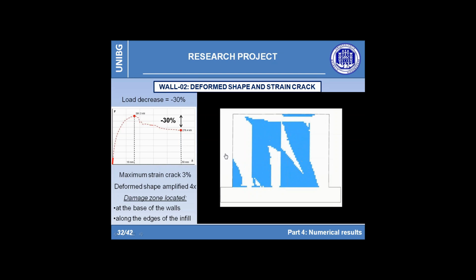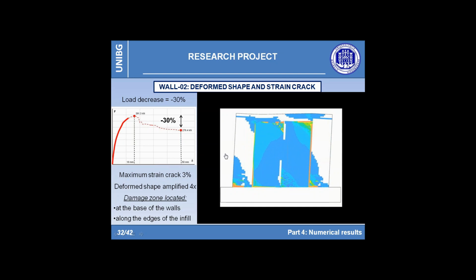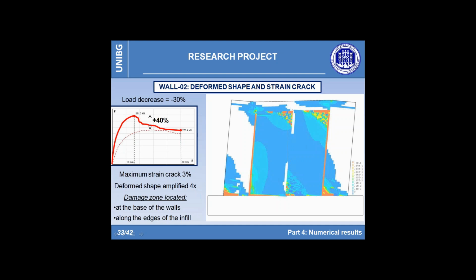As previously done, the video of the deformed shape evolution with the increasing top displacement is reported, highlighting the zone affected by cracks. It can be noted how the infill panel tends to quickly exhaust its structural resources, highlighting, starting from 0.5% drift, widespread damage and significant cracks at the interface with the structural walls and along the edges with the outer frame.